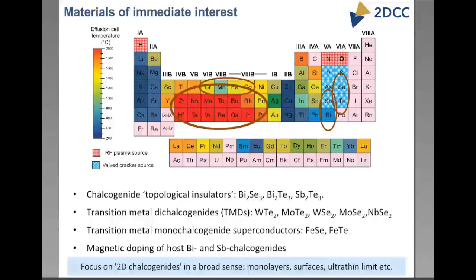And then finally, what we also want to do, and are currently interested in, is taking many of these materials and magnetically doping them. So for example, if you take bismuth selenide and introduce a magnetic dopant like chromium or manganese or iron or cobalt, these have interesting properties. So it's a very broad sense of what 2D chalcogenides encompass.